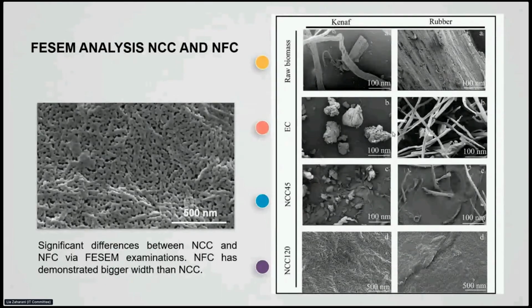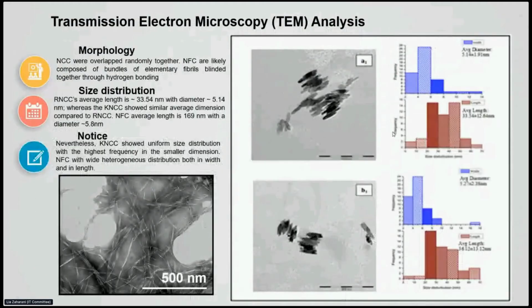For nanofibrillated cellulose, it clearly gives a little bit higher dimension compared to nanocrystalline cellulose, according to the FESEM images. For determining the dimension, we're using TEM analysis.